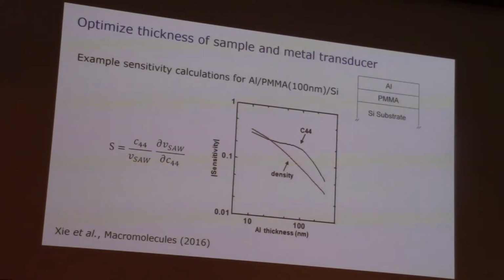And this just tells you that there's some optimization to do about how thick the layer should be. Say if you want to measure the elastic constants of a polymer, this is just how you optimize the thickness of the aluminum in order to get the best sensitivity to the elastic constants. And so, it just says, well, pick the aluminum thickness to be about 100 nanometers, and you can get a pretty decent measurement of the elastic constants of a polymer film. And we use these kinds of things to design the experiments. Right? So this is just that.